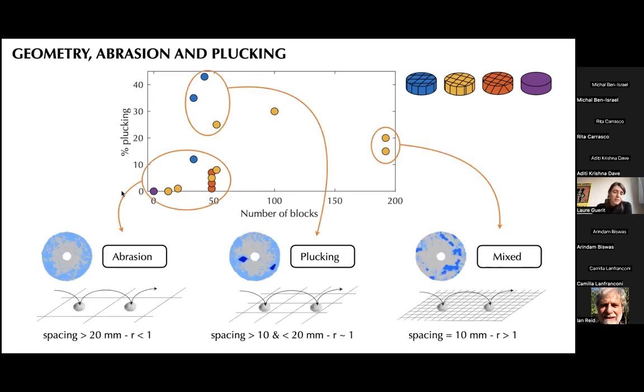So at the bottom here, we have experiments dominated by abrasion. And as I said, these experiments are the ones with only a few fractures, so that the size of the blocks is always larger than the size of the sediment we use. So we think that in that case, plucking cannot occur, there is only abrasion and erosion is limited.